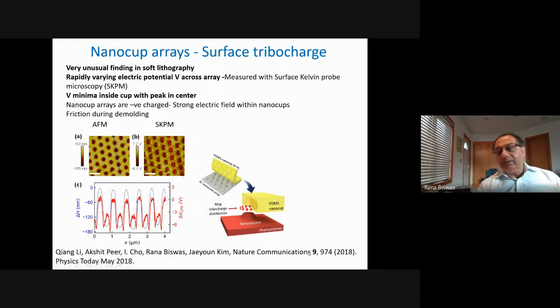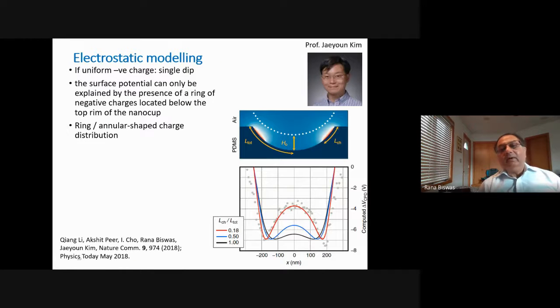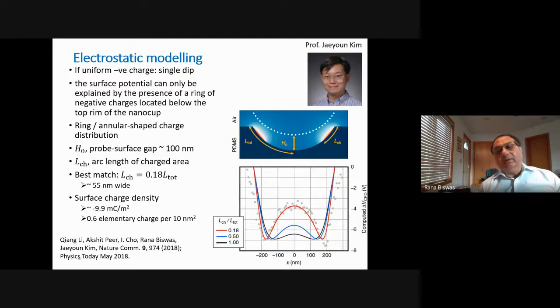So these results were published in Nature Communications in 2018. And to understand them more carefully, together with my collaborator, Professor J. Kim, we did electrostatic modeling. And here, the idea is you put charge on the surface of this nanocup. And in white is the trace of the AFM tip as you scan across the surface. Now, if you have uniform negative charge, then you get the trace over here, which is the black line. So sure, it shows a deep minimum in the nanocup, but it is unlike the experimental data, which is shown by the dots here.